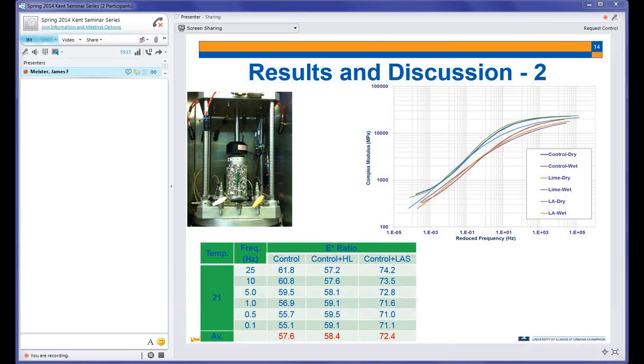Numerically speaking, this is what I did. For the control, the E-star ratio was 61 to 55. We take the average of this, as they did. It is 57.6. Similarly for the lime, it's 58.4. And finally, for the liquid anti-strip, it's 72.4. What this is saying is that there is almost a 50% drop in the complex modulus for the control and the lime after 5 freeze-thaw cycles, while for liquid anti-strip, 72% was still sustained of the original complex modulus after conditioning.